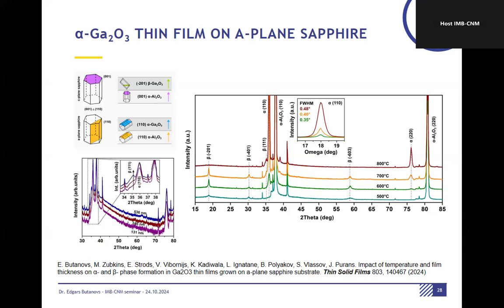And if you do a very nice growth process, you can stabilize this metastable phase even at higher temperature. What we explored first of all was the impact of the substrate temperature. It was counterintuitive in the beginning that you elevate the temperature of the substrate and you stabilize a metastable phase. Logically it should be the opposite: if you increase the temperature, it should move to the thermodynamically most stable phase. But it's the opposite. The beta phase disappears and the alpha phase appears at higher temperature.